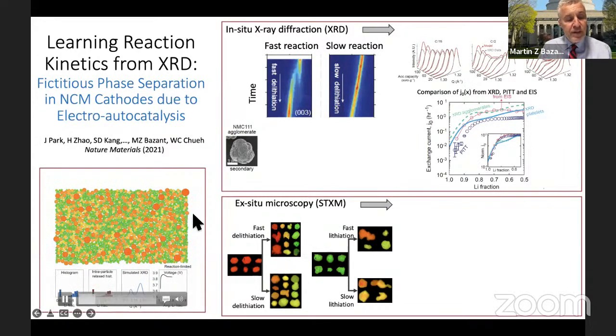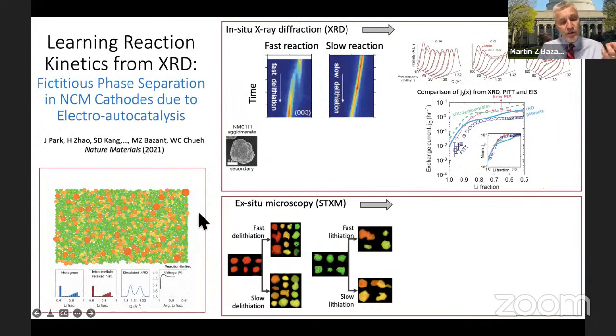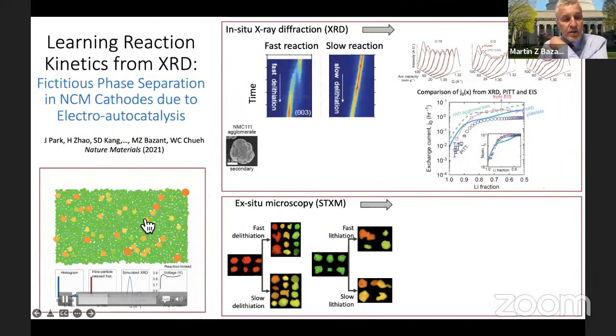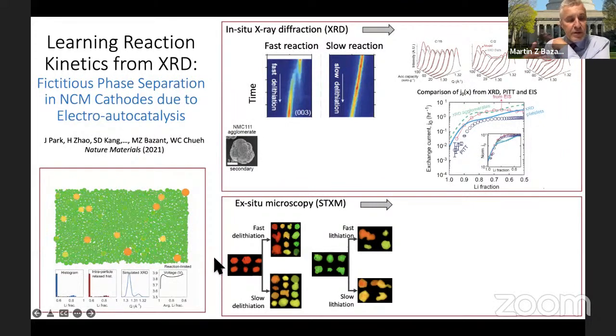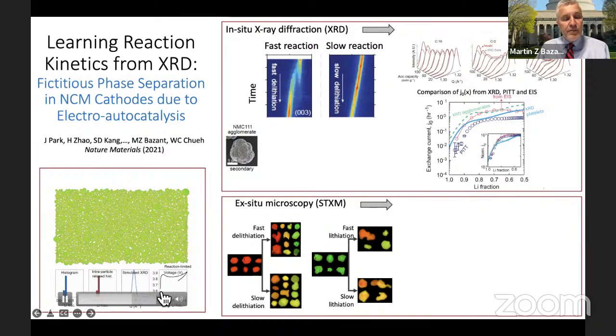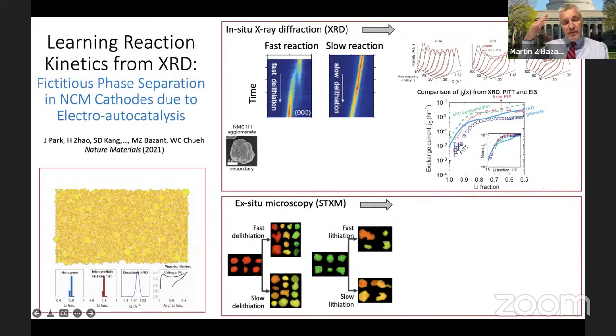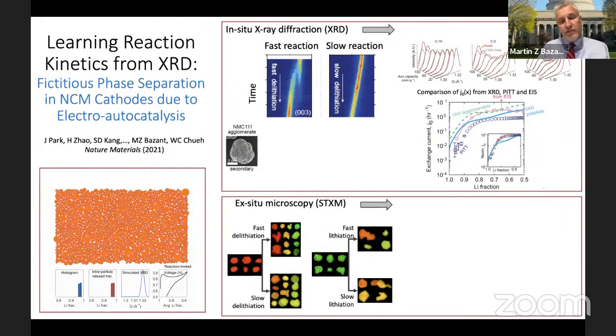And notice it's very heterogeneous. In this case, the small particles are delithiated before the big ones. And then eventually they all finish. But if you now insert again, you find that it remains uniform. So you'll see that movie play, and now the green is going to turn back to red in a more uniform way. And you can see the voltage being predicted here as well. And the reason, again, is that as you're inserting lithium, the rate is slowing down, it's autoinhibitory, and that's stabilizing. And when you extract it, it's destabilizing.